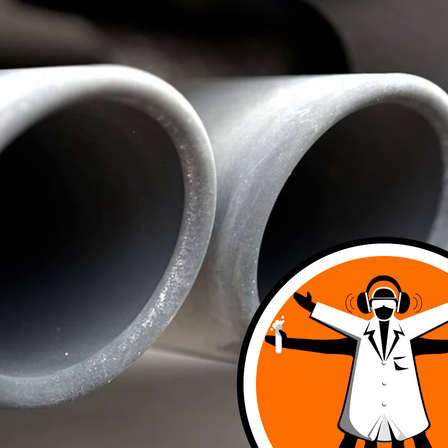So platinum is a very expensive metal, and usually reactions are carried out on platinum particles. But the only platinum particles that can interact with carbon monoxide are at the surface of the particle. The platinum atoms in the middle of the particle can't contact the carbon monoxide. We're paying for them, but they're being wasted. So we want very small particles, or even just a single atom of platinum. The problem with very small particles is they love to become big particles. Whenever you heat them up, they love to become big particles, and you've lost the advantage. So one role of the cerium oxide is to keep the platinum atoms apart from each other.